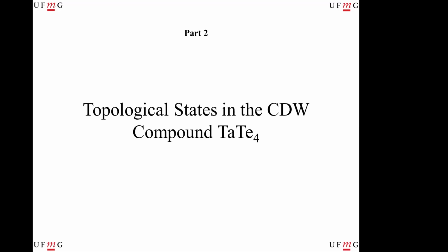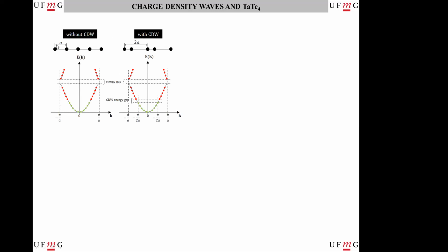The last project that I will present uses a little bit more the powerfulness of photoemission spectroscopy, which is the topological states on the CDW compound tantalum telluride. For the ones that don't know, a CDW is a charge density wave. A charge density wave works like this: imagine that you have a one-dimensional crystal with a lattice constant of a, and then there is a lattice distortion in the sample where some atoms move positions, and there is now a new periodicity in the crystal. Here you have the band structure of the system without the charge density wave. We have, for example, in green the states that are occupied, and in red the states that are non-occupied. And here we have, for example, a metallic sample.